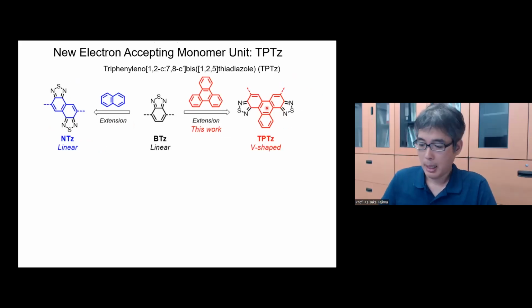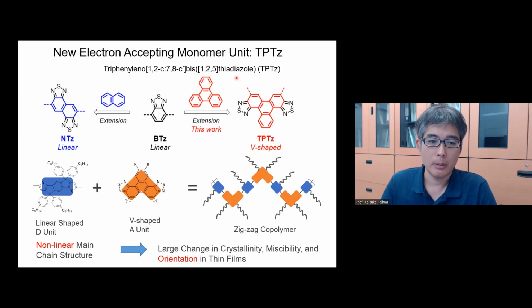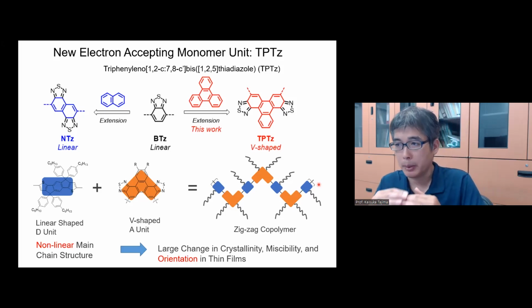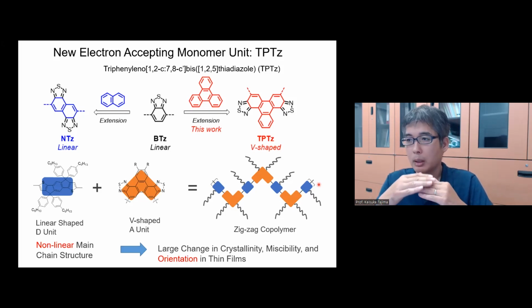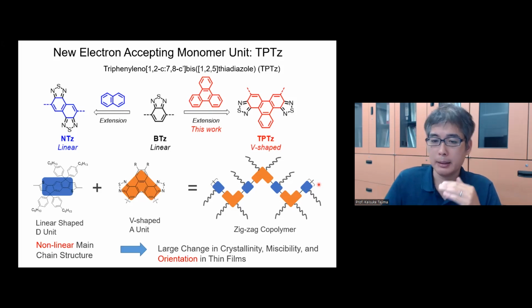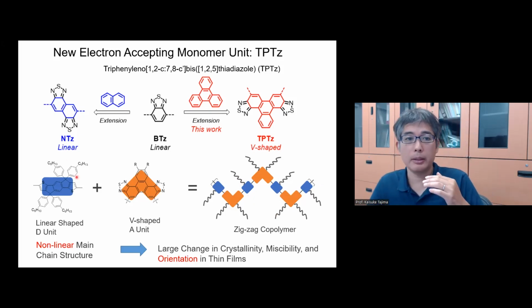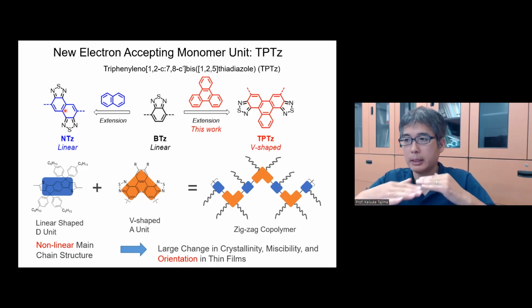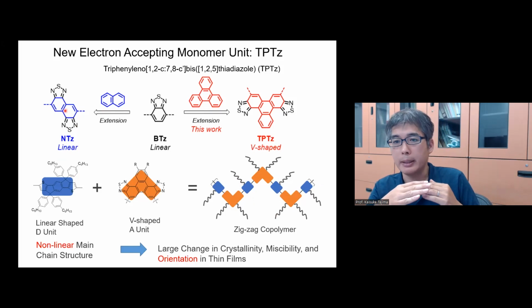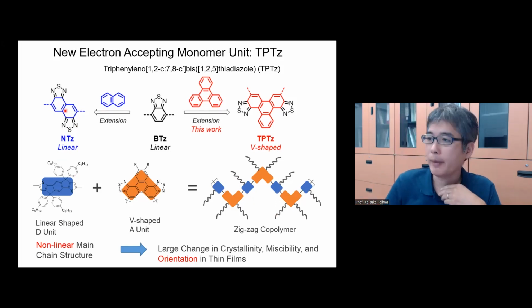We call it TPTZ. What we expect here is that this bent-shaped monomer unit is combined with a linear-shaped unit through a coupling reaction to get a high molecular weight polymer. The resulting polymer is a kind of zigzag copolymer, but we want to keep the planarity of the polymer because it's important for charge transport and light absorption. Assuming that this zigzag-shaped copolymer can be obtained, it could change the orientation compared to the linear version. We thought that this zigzag-shaped copolymer probably has a tendency toward face-on orientation in the film, and that it probably persists in the bulk heterojunction film. That's what we expected.